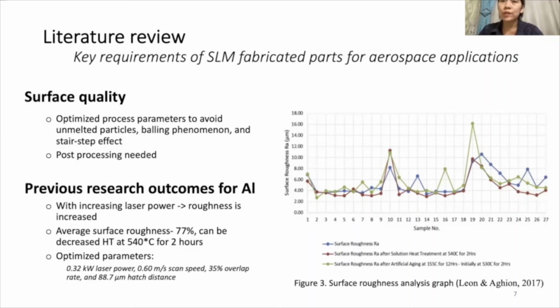In general, additive manufacturing parts should undergo post-process surface finish, such as machining, grinding, or chemical polishing, to be applicable in the aerospace industry. Recently, experimental studies were done on the influence of process parameters and heat treatments on the surface quality of selective laser melting fabricated samples. The important conclusions are as follows. First, variations in surface roughness were observed, which is due to the inherent random errors of the manufacturing system. Second, the surface roughness increases with increasing laser power level, and the best results were depicted at 0.32 kilowatt laser power.